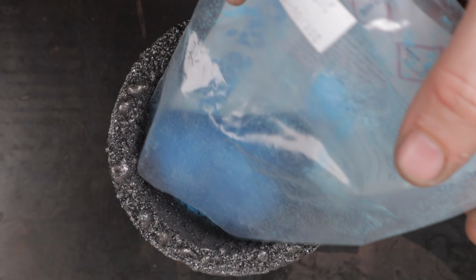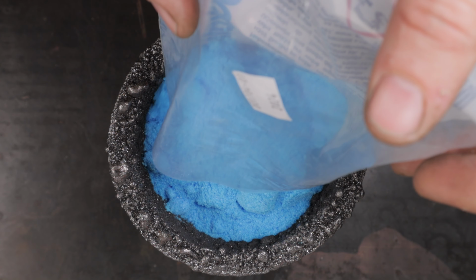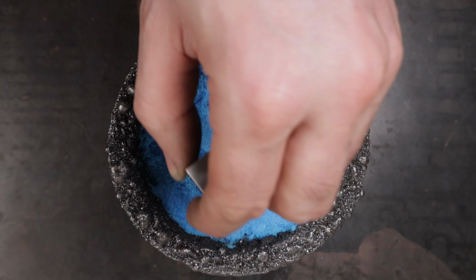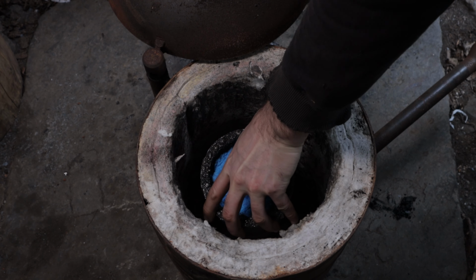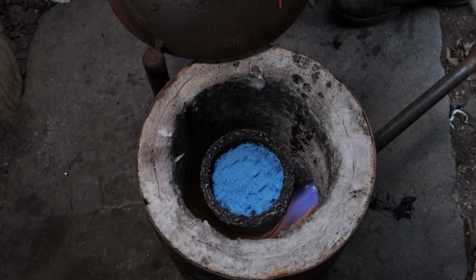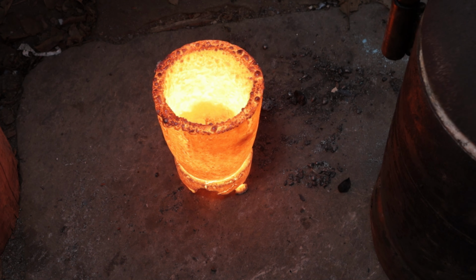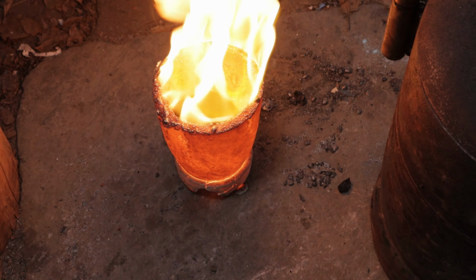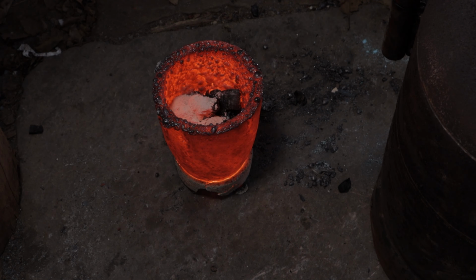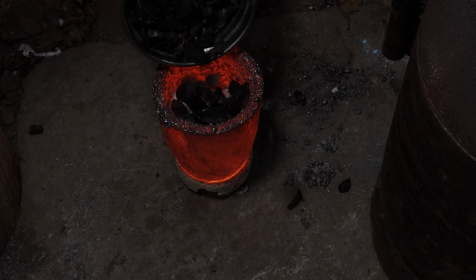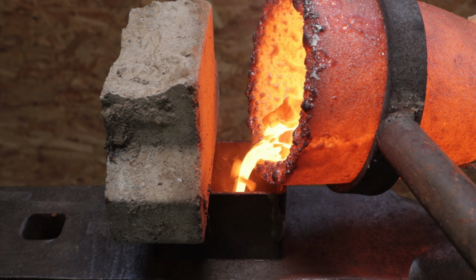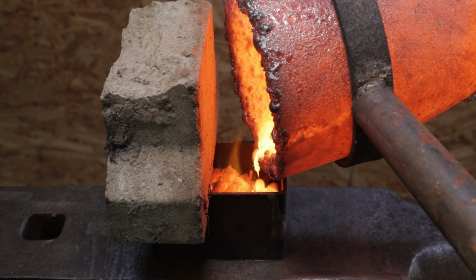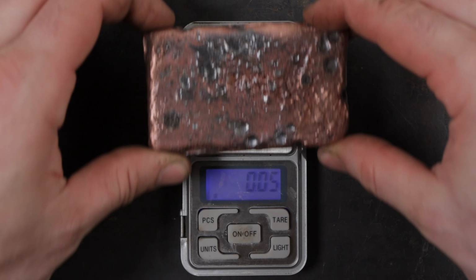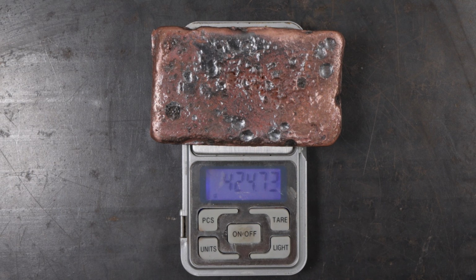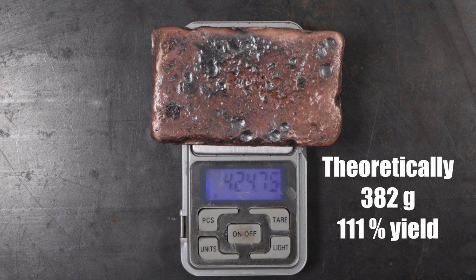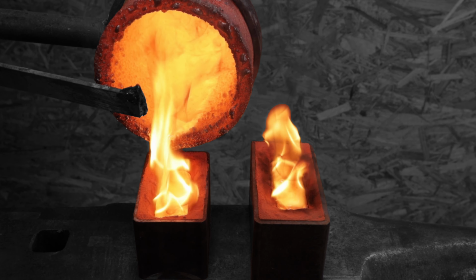Let's deal with the rest. This time I will add carbon at the end to avoid any sulfur dissolution in the metal. I added slag from the previous melt, as well as some lime, borax and charcoal on the top. This time I had no problem. The ingot looks fine and the yield is 111%. Well, that's because I extracted copper from the slag from the previous melt.